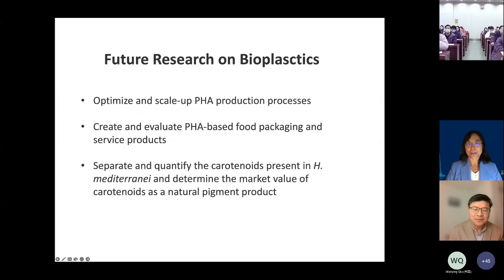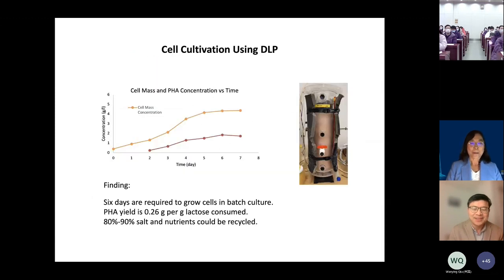I thought I didn't have time, so I just went through the yield very quickly. We actually have papers published, and I'll be happy to share with you. In this case, this graph, I didn't have time to go through in detail. Here is the yield. About 26% of lactose is converted into PHA. If you work with the volatile fatty acid, there's about 32% conversion. So 32 to 35% conversion from volatile fatty acid to PHA. Based on the sugar, in this case lactose, 26 is just one number, but we have a range. So the ballpark is about 30% conversion.